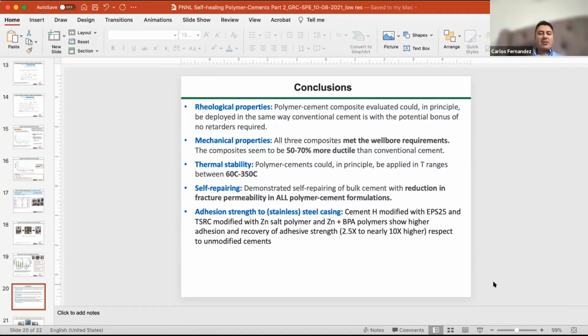We don't know. We haven't done any tests above 30 days, but we can do some accelerated tests. We can immerse these polymer cements in mineral acid, pH 1, for maybe a year, and look at the integrity of the polymer using NMR, and also the content of the polymer using total organic carbon tests. That's a way to accelerate the aging and maybe have an idea of how it will behave. One year in acid could be equivalent to, I don't know, 10 years in a less harsh environment in a geothermal wellbore.